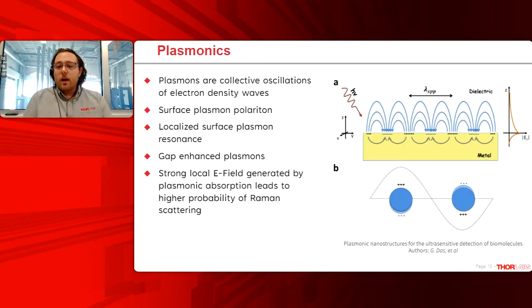This is when light of a correct momentum condition is incident on a metal dielectric interface. And if the engineering of these structures and these interfaces is correct, you can very efficiently couple that light to that surface and couple it to a plasmon. So in this case, you're converting this light energy to this collective oscillation of electron density waves that propagate along that interface.